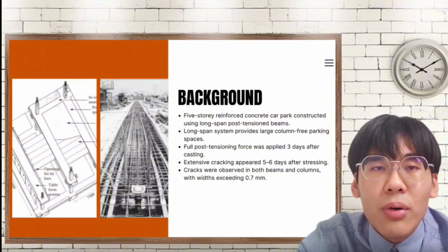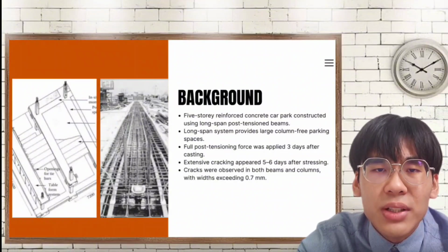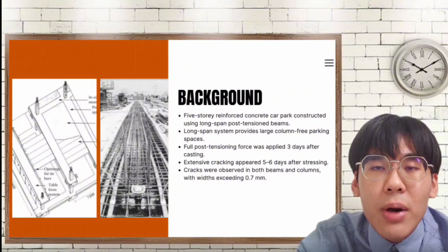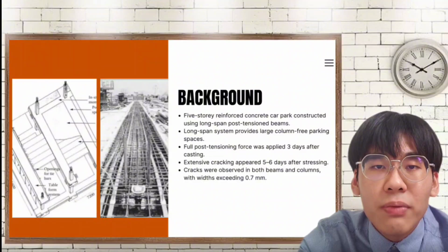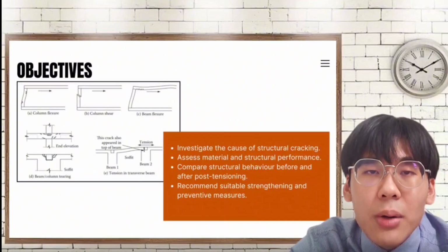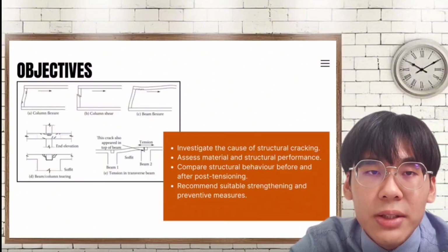These cracks were found not only in the beams, but also in the supporting columns, with crack width exceeding 0.7 mm, which is well above the acceptable serviceability limit. Based on this case, our study has 4 main objectives.